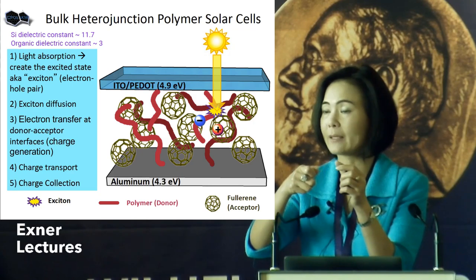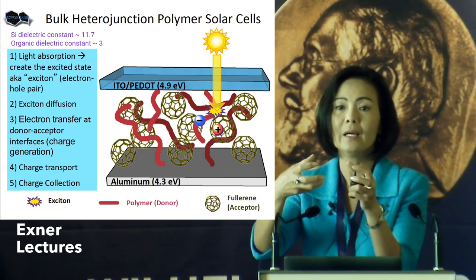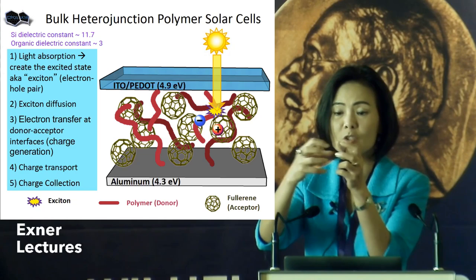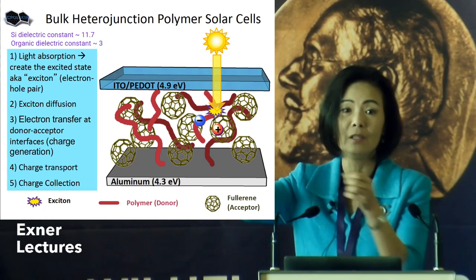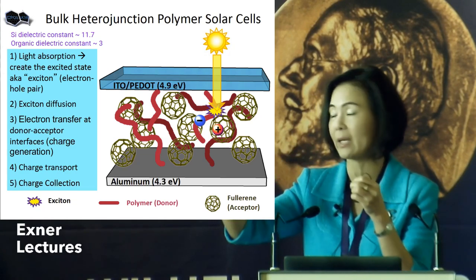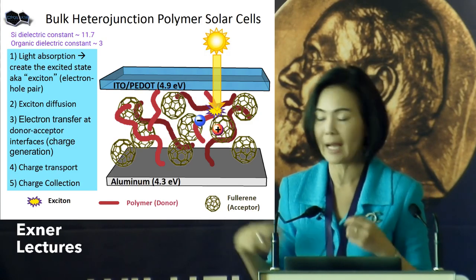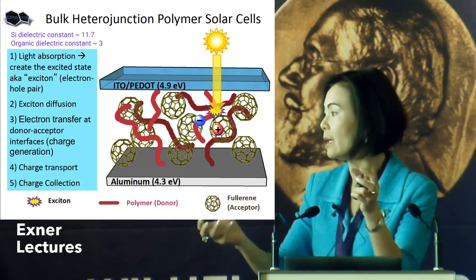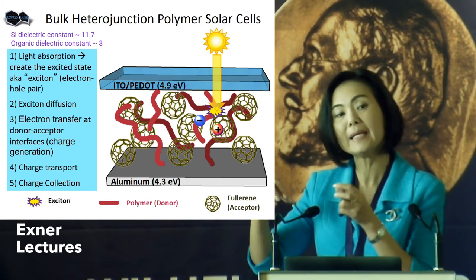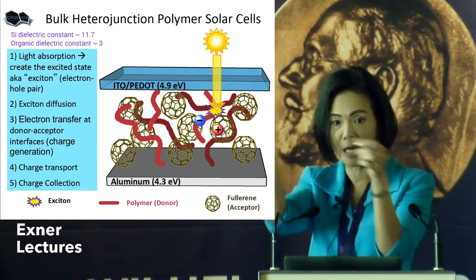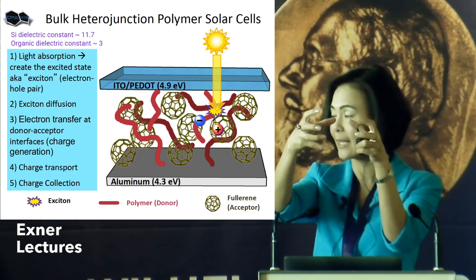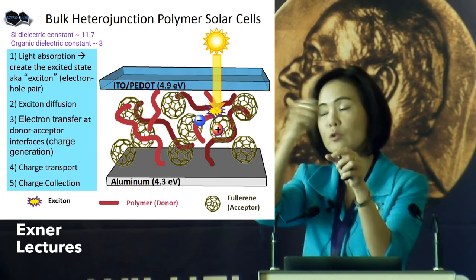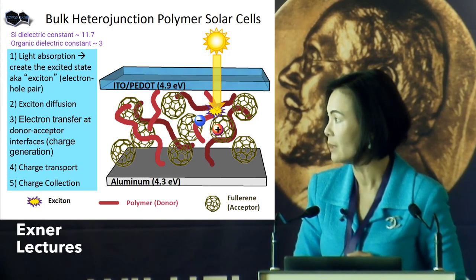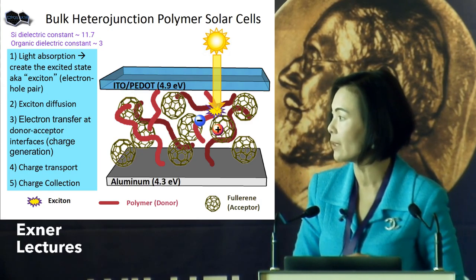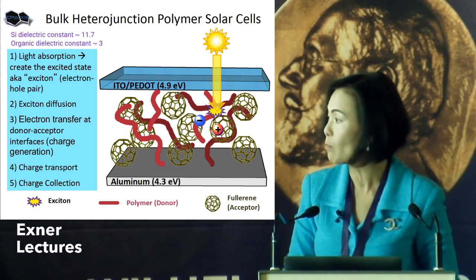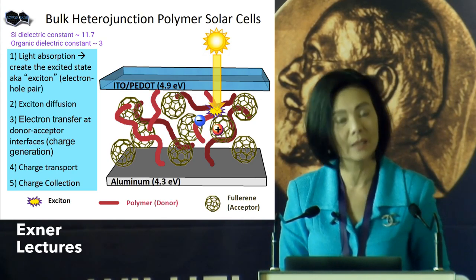If you shine light on it, the material absorbs light, you create the exciton or the excited state, but the excitons are strongly bound together. It's difficult to free them up to form free carriers. So to do that, the organic people back then had to take the donor material and blend it with an acceptor so that you can separate the charge. You create the exciton and it does ultra-fast electron transfer from the donor to the acceptor. And so that's how you overcome the exciton binding energy to extract the charged carriers.